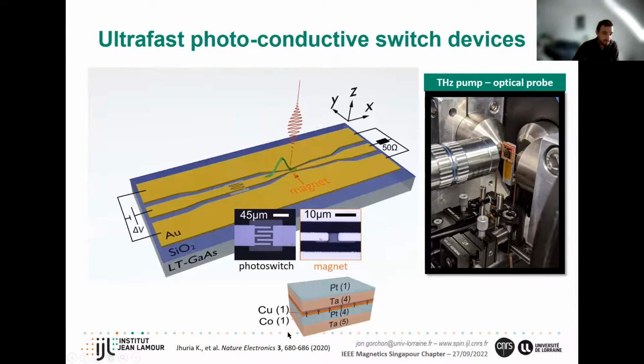So the type of samples that we've been looking at are these. So we have platinum, cobalt, thin cobalt that is perpendicularly magnetized, and then tantalum on top. We also have a thin copper layer there.